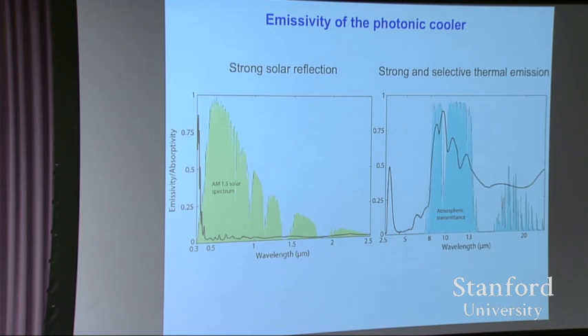Since this is just a thin film deposition, in principle, this can be directly applied to large scale. As far as optimization is concerned, these are optimized within the constraint of a particular vendor that we use to fabricate this. So it's certainly by no means an optimal structure. In fact, for example, you look at the emissivity here, it's only on the order of 60 to 70%. And certainly there's room to improve it further. And even within the constraint of multi-layer film, so they can do just thin film deposition without lithography, one actually can improve this a lot more.